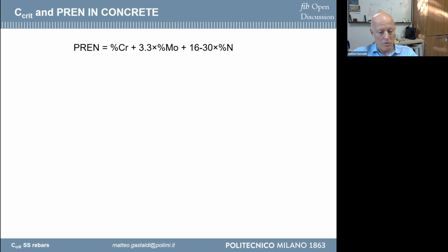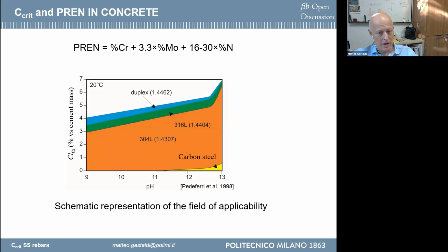The problem is that when we move from neutral solution and acid solution to an alkaline solution that is related to what is normally present in concrete, PREN is not effective. So we cannot use PREN in order to have an idea about the resistance to corrosion related to the initiation of corrosion induced by chloride if you are in an alkaline environment, because the effect, for example, of molybdenum is lower than the effect that we have in a neutral solution. You can consider using this kind of number to make a selection of the stainless steel if you are in carbonated concrete, in which the pH is not 13, but is below 9, okay?